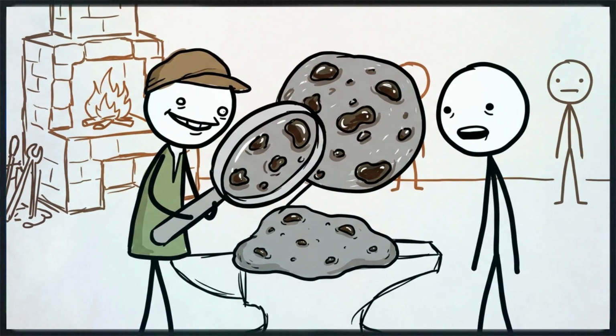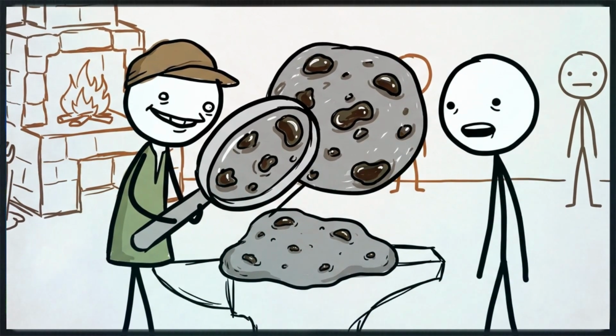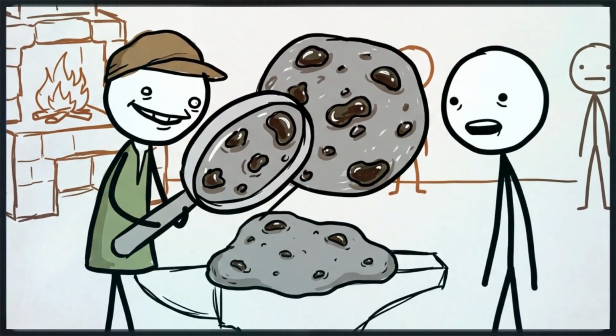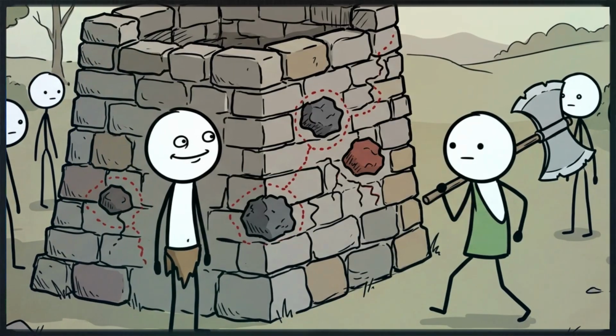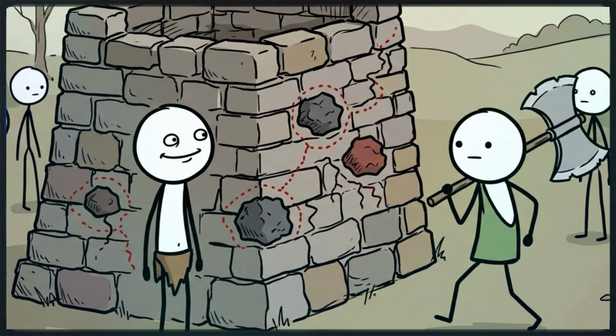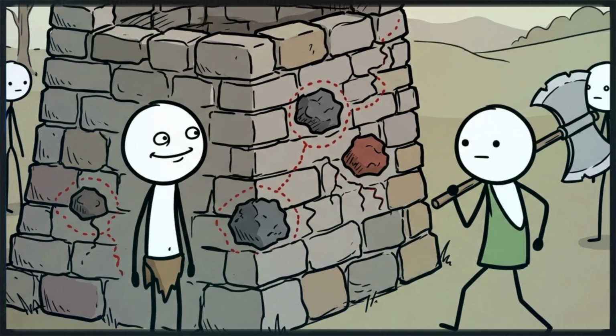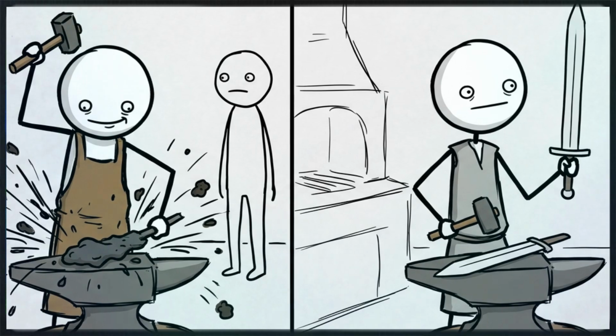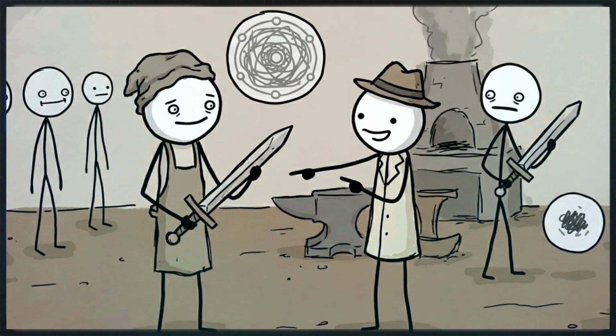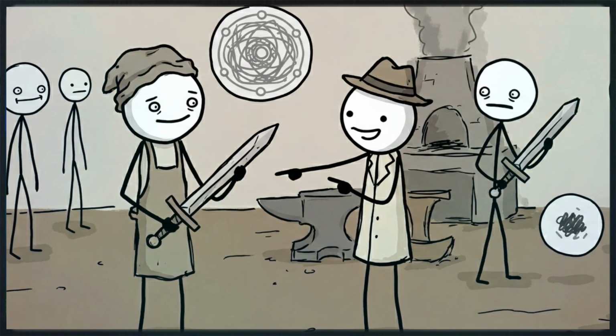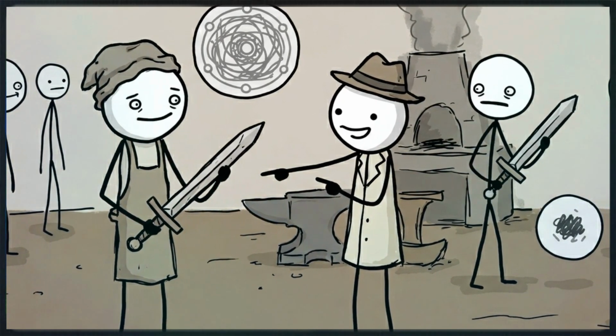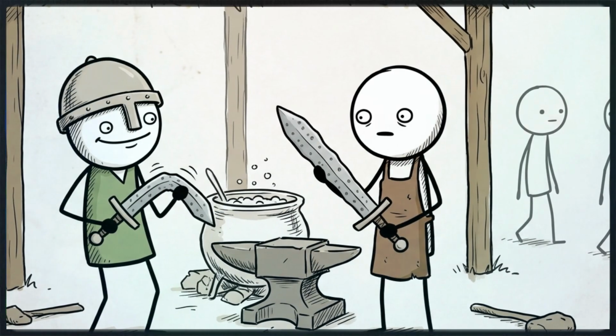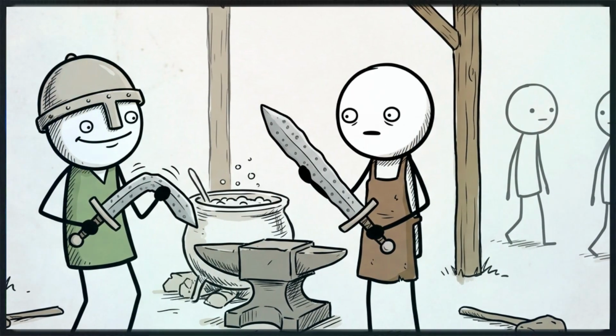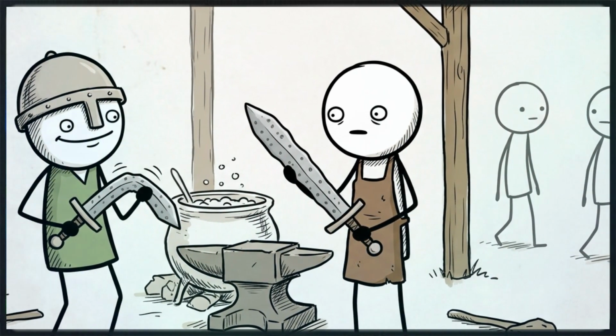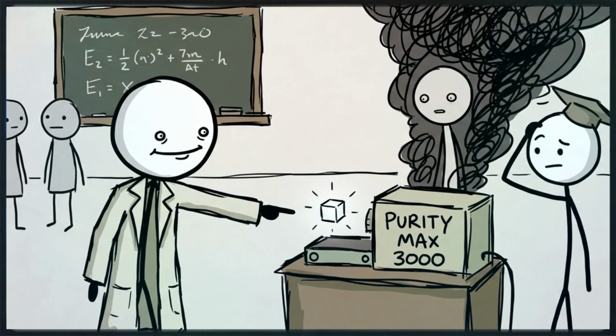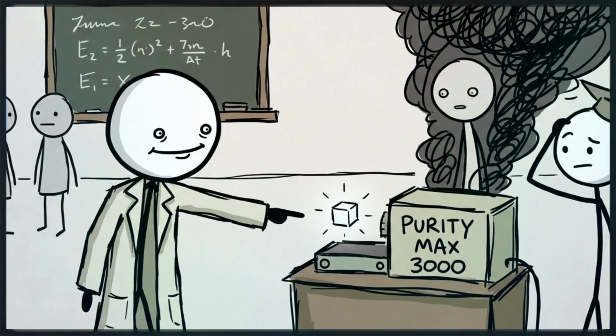As a result, the metal was riddled with microscopic pockets of slag, glassy, non-metallic impurities left over from the raw ore. Every piece of slag was a structural weakness, a fault line waiting to shatter upon the kinetic impact of a heavy battle axe. The Ulfberht, however, contains virtually zero slag. It is flawlessly pure, and its carbon content reaches up to 1.2%, nearly 3 times higher than standard European swords of the era. This perfect distribution of high carbon is what granted the blade its lethal combination of extreme hardness and kinetic flexibility. But achieving this level of purity introduces a massive thermodynamic paradox.